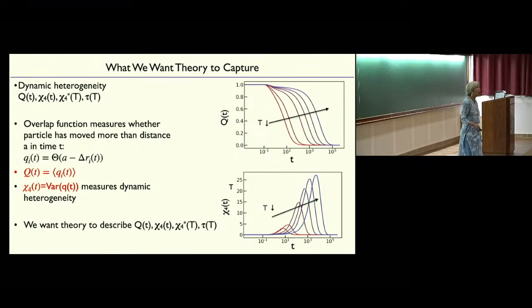I agree with that. We don't know how high dimensional that is at higher temperatures compared to lower temperatures, right? The other thing I would say, one thing that Rahul Chacko has found, in work that we did with Olivier Dauchot, Julie Barolli and David Reichman, is that when you start getting below the mode coupling temperature, you see a crossover to where elasticity becomes important. So elastic facilitation of rearrangements becomes important. That's the one thing that we see. But you don't expect that the qualitative nature of the barrier will be different? It doesn't seem to be very different as far as we see. No. You can have a local definition as well.